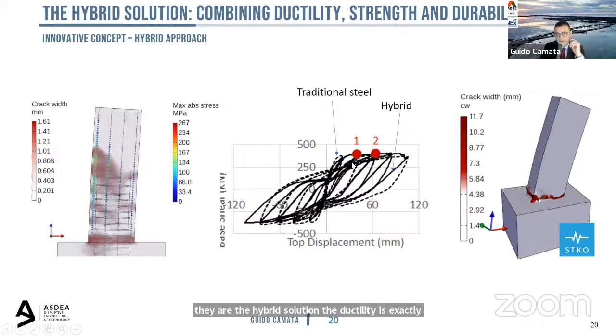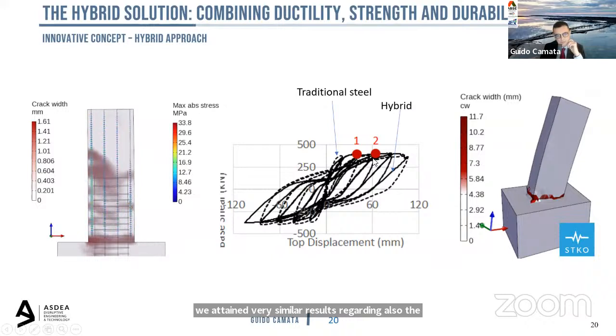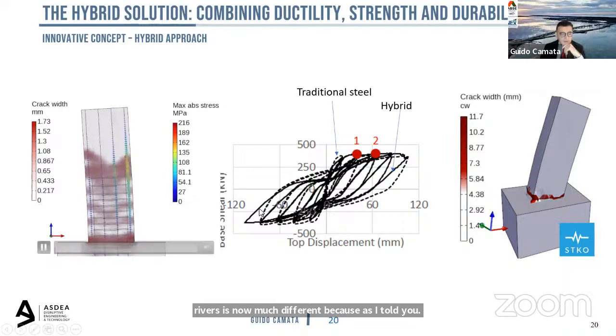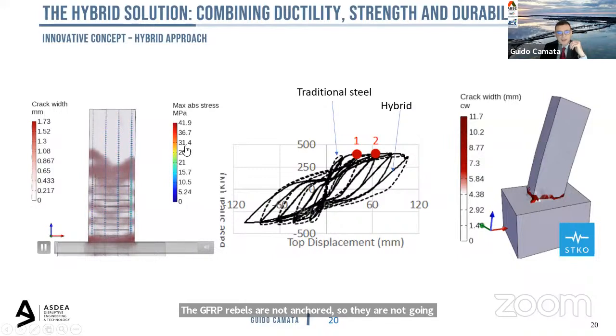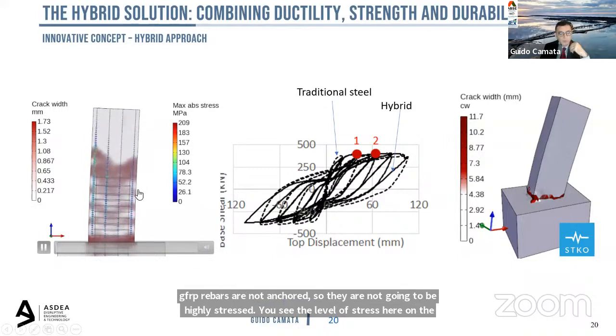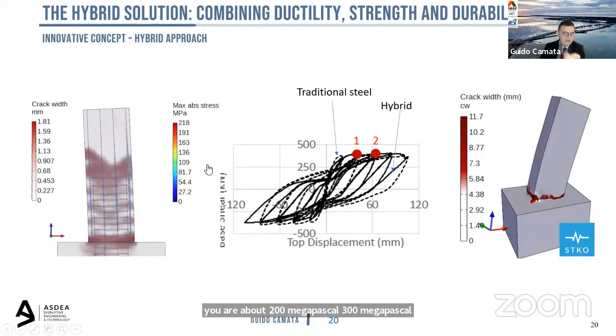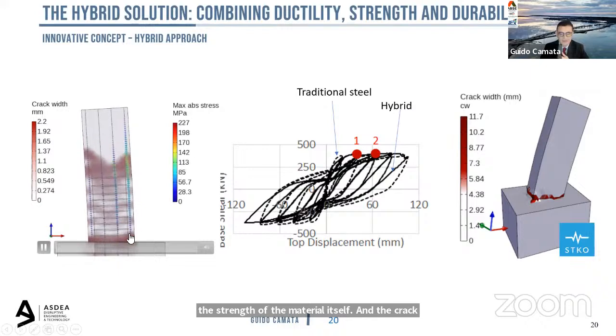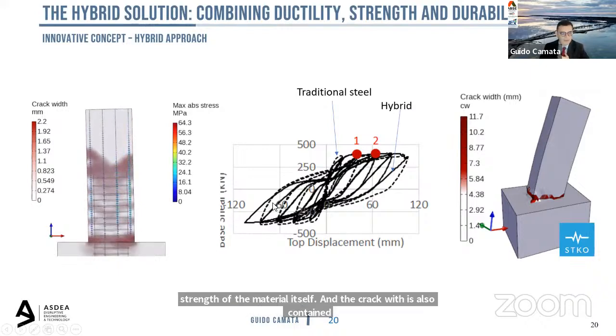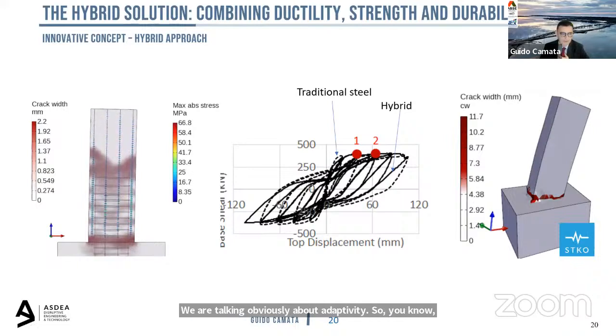We obtain very similar results regarding also the concrete cover spalling, and also the buckling of the rebars is not much different because, as I told you, the GFRP rebars are not anchored, so they are not going to be highly stressed. You see the level of stress here on the left. You are about 200 megapascal, 300 megapascal, so way below what is the strength of the material itself. And the crack width is also contained. We are talking obviously about high ductility. So, you have 2 millimeters at the base, but this is expected because you are going to have rocking of the system. So I think it's very interesting.